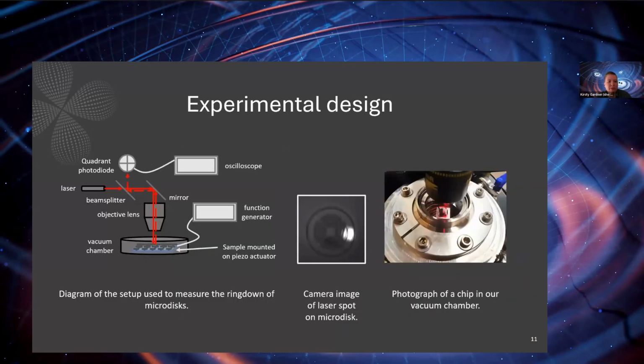So here is our experimental setup. This is what we use to measure the mechanical quality factors of our microdiscs. So our chip containing the hundreds of devices is put into a vacuum chamber so that we can pump out the air and make sure that the pressure damping isn't limiting the measured quality factors. And our sample is mounted on a piezoelectric actuator, which itself is hooked up to a function generator. And so we can send a driving sine wave to the piezo actuator to start the discs oscillating, and then we can turn the signal off and measure how the amplitude of oscillation decays over time, which lets us extract the quality factor and then figure out the loss.